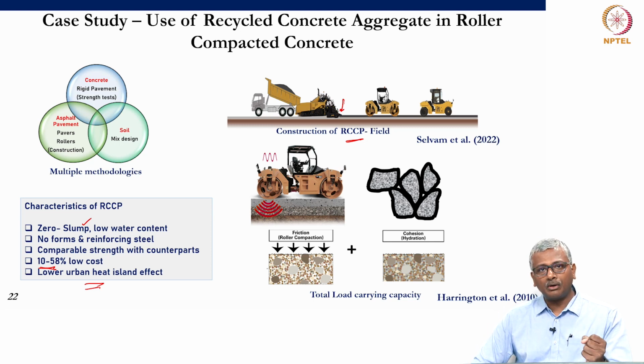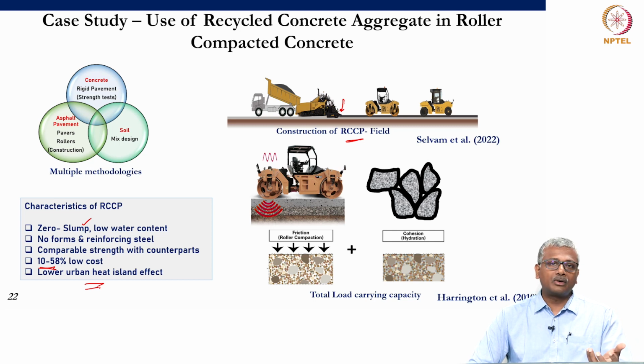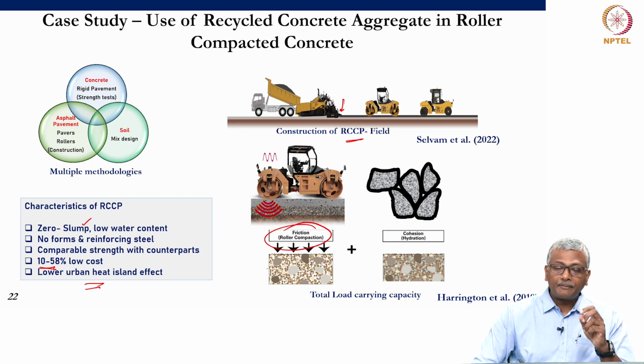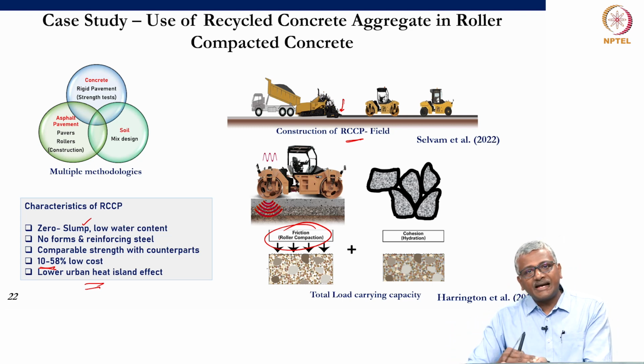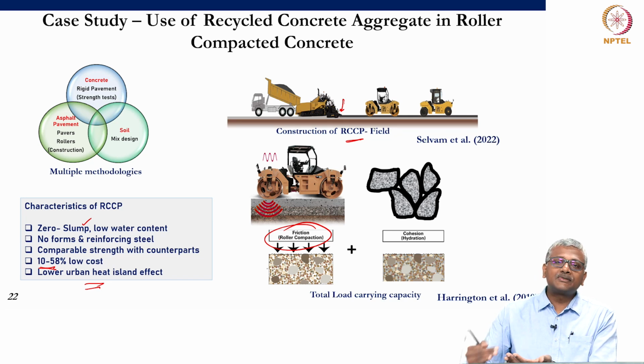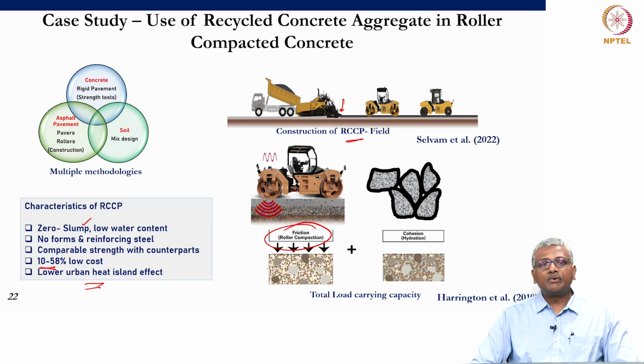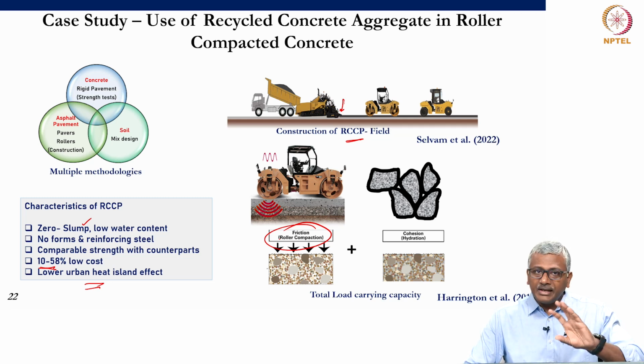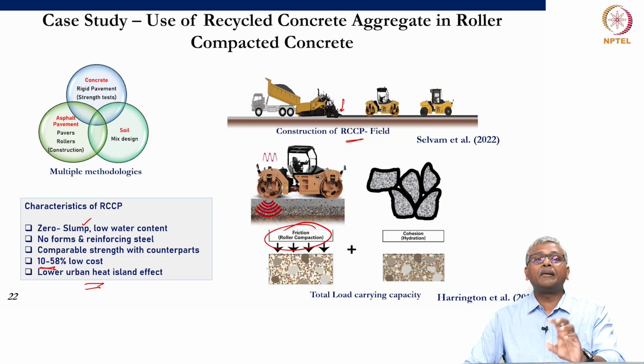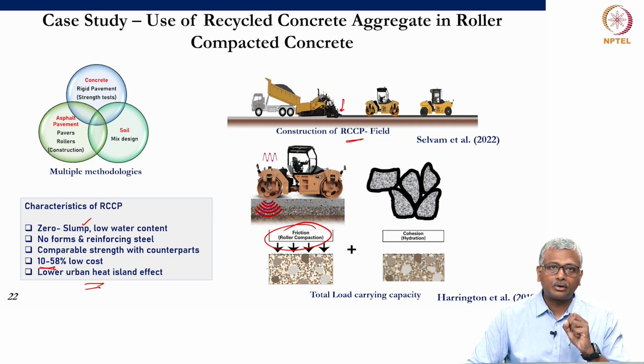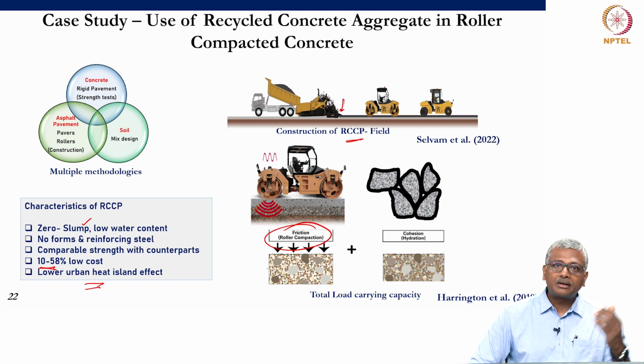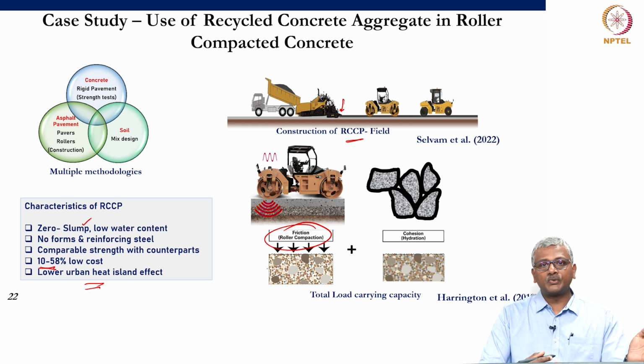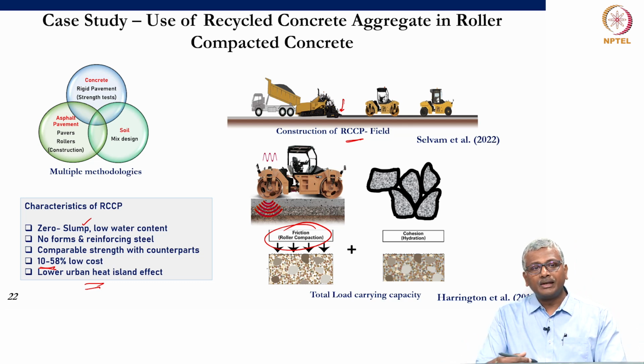Okay. So, what essentially can be done in the case of roller compacted concrete pavements, because you do not need much slump at all, you can then think about utilizing recycled concrete aggregate in such purposes. Okay. But the issue is now you need to figure out whether the roller compaction, that means the application of pressure by the roller, is going to be as effective in the concrete with recycled aggregate as it is with conventional aggregate, right. So, that is the primary challenge when you try to design such special types of concrete. So, now is your recycled concrete aggregate affecting compaction? That is the challenge in recycled concrete, roller compacted concrete pavements. We earlier talked about workability, but compaction, as you all know, is also a feature which defines workability. So, let us take a look at what happens when recycled aggregate is used in roller compacted concrete and whether we can achieve the same level of compaction or not.